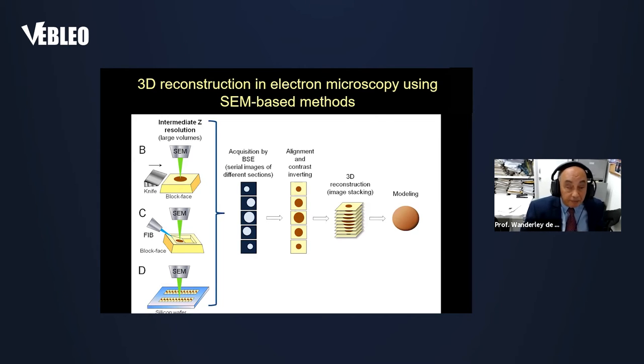In this slide here, I present two types of possibilities. One is to have a knife inside a scanning microscope, and this knife can expose one surface that I want to analyze. And then I can do some successive cuts on the surface. The other possibility is to use a gallium ion source, and this gallium also removes 10, 20, 30 nanometer thick slices from the surface of the sample. And in all cases, we can observe the successive planes of focus of the structures that we are observing. So that I have hundreds of successive images of one given surface that can be reconstructed using computer techniques.